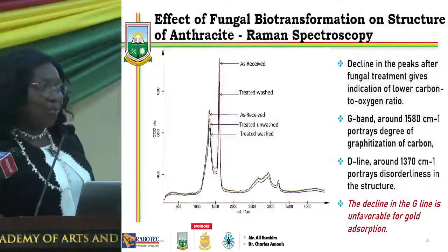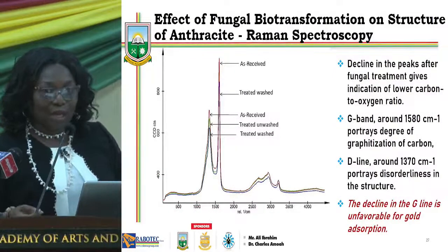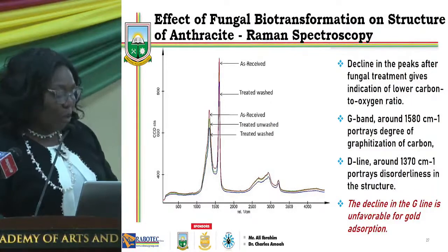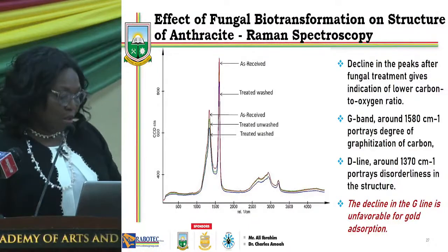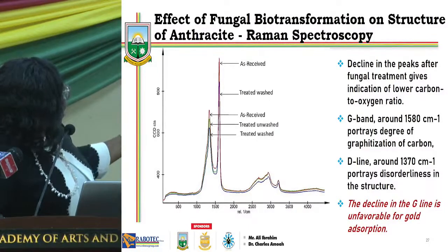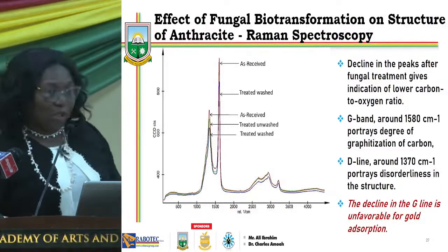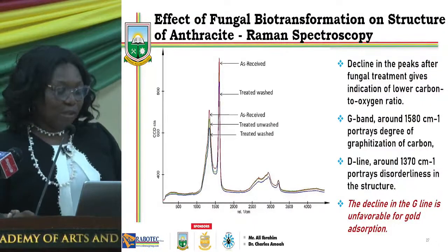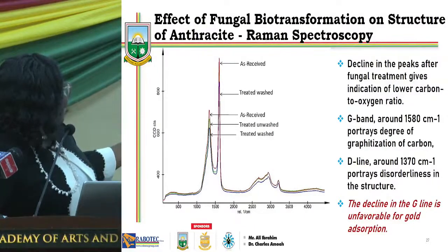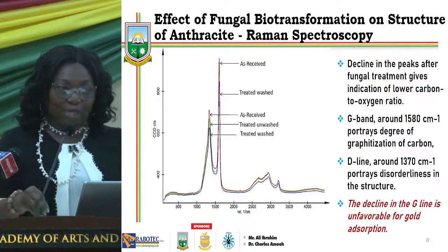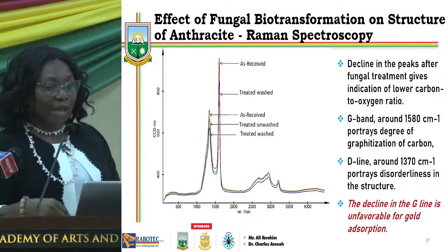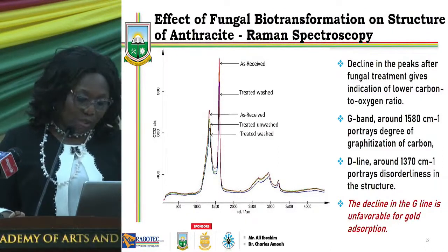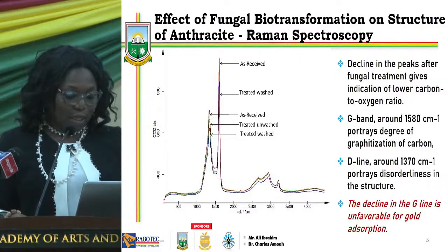Then we have Raman spectroscopy, and this also gives us an idea of the structural components of the carbon. Looking at the peaks, all the peaks reduced. The red one is showing the as received, and the bluish color is the treated. Of importance to us is the peak here, called the G band, which shows the graphitic structure of the carbon. From this diagram, that structure also reduced, and therefore it led to reduction in gold absorption.